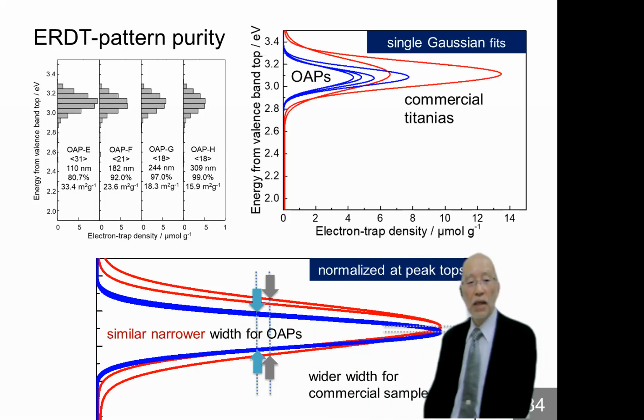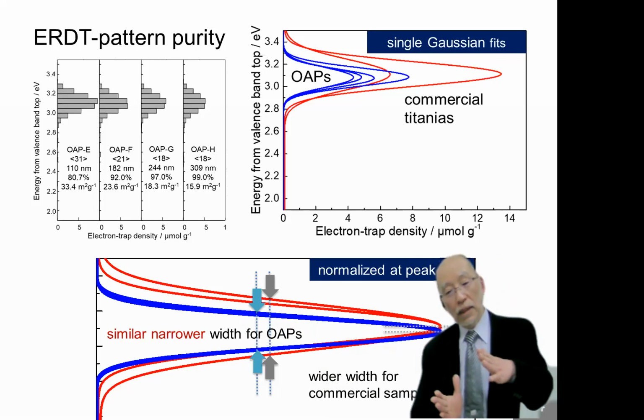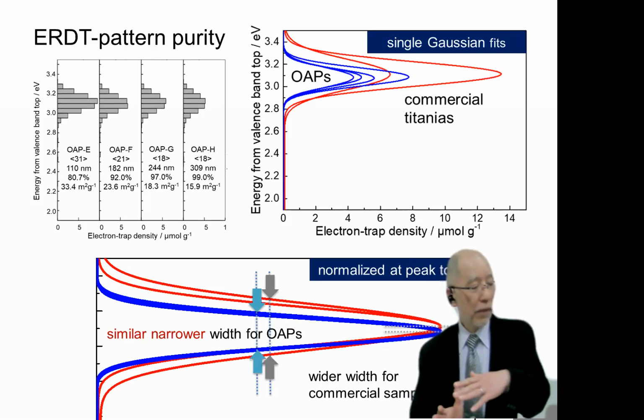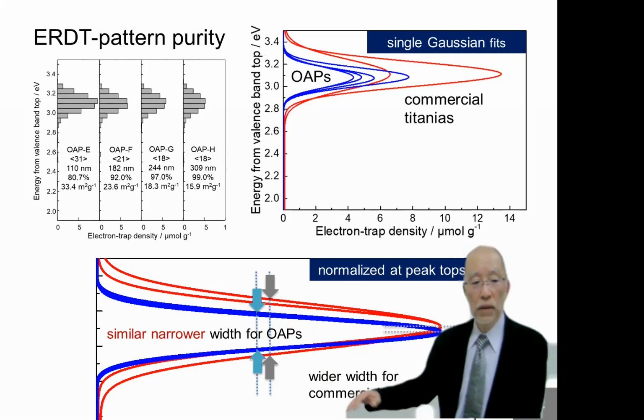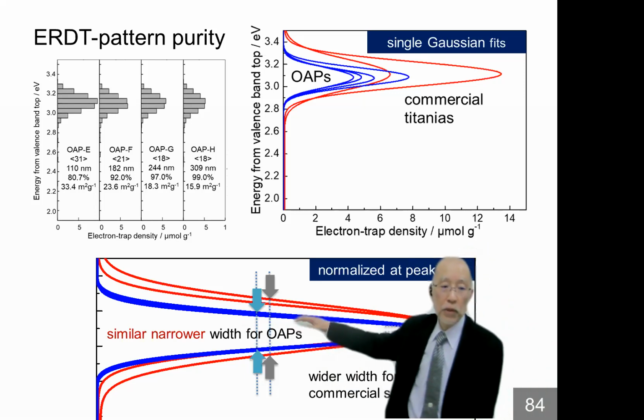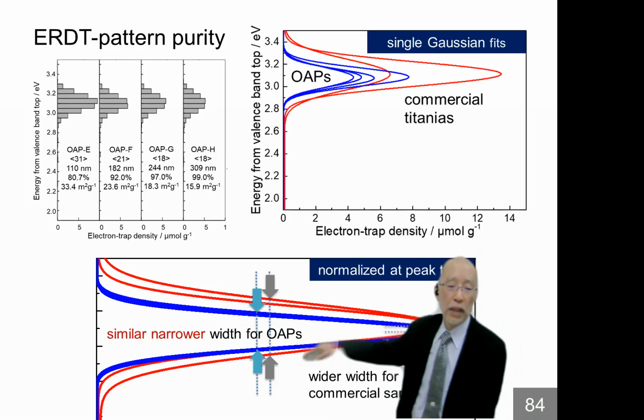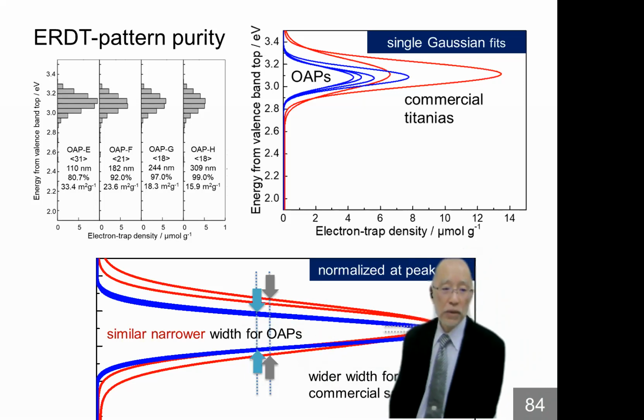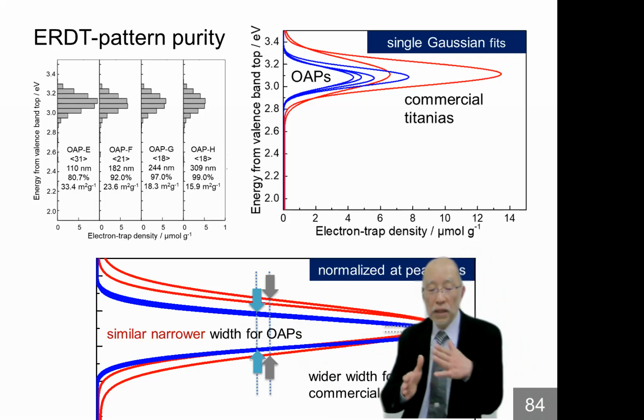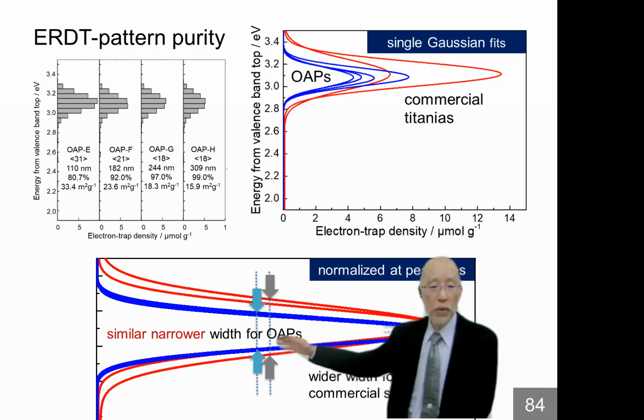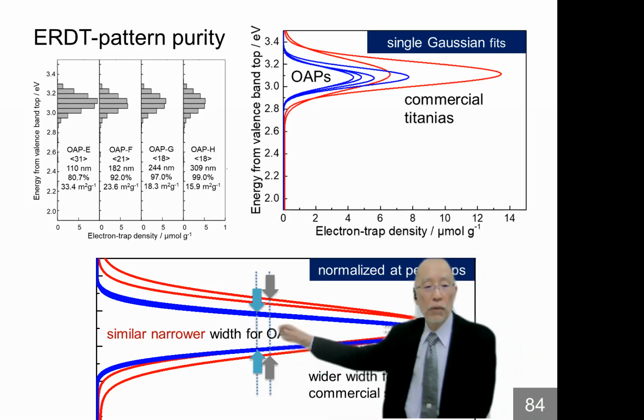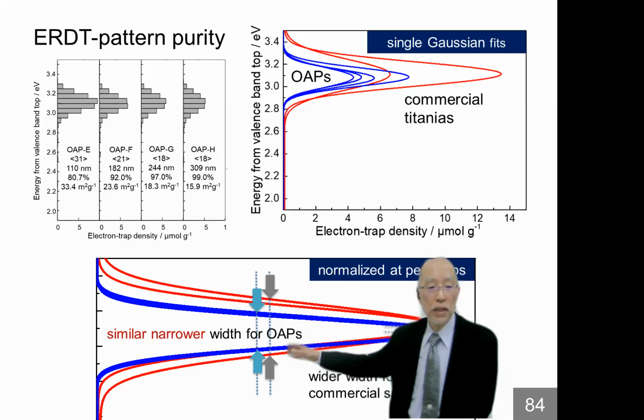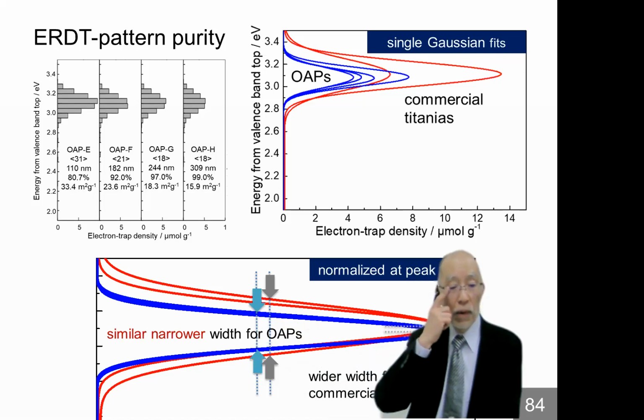And that means probably a different type of surface facet gives a different ERDT peak position. And they are a mixture for commercial samples. Different surfaces are exposed. But for OAP, only 101 facets are exposed. So therefore, a very narrow one.